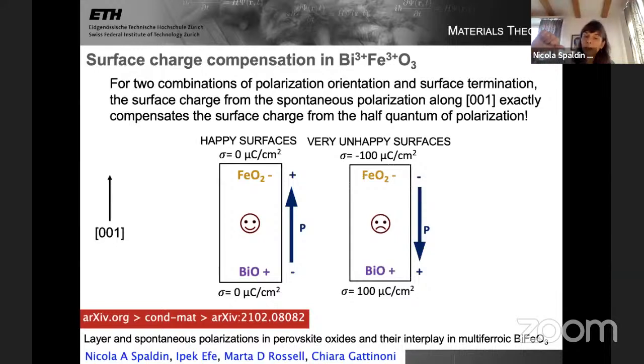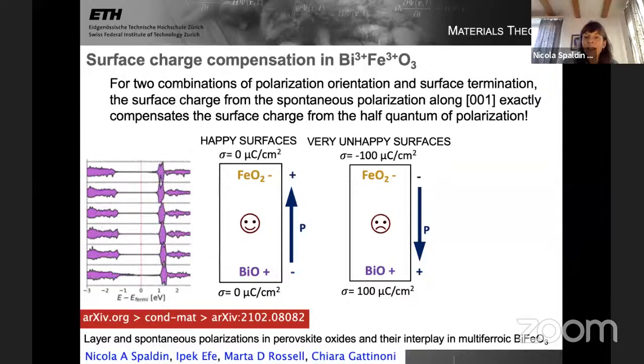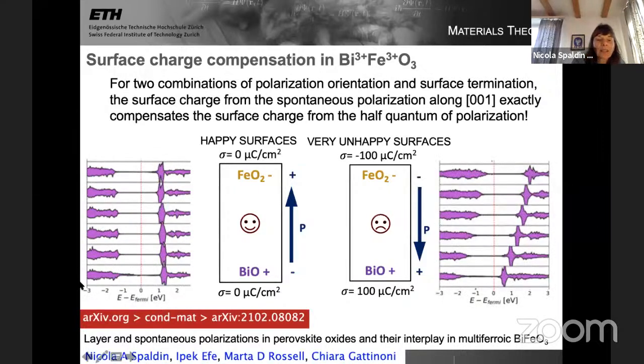Conversely, if I try to switch the polarization, my surfaces are doubly unhappy. They have the unhappiness from the surface charge from the spontaneous polarization, combined with the surface charge from the internal polarization. And we can see this in the calculated density of states. This is the density of states as a function of energy, layer by layer, through my bismuth ferrite film.